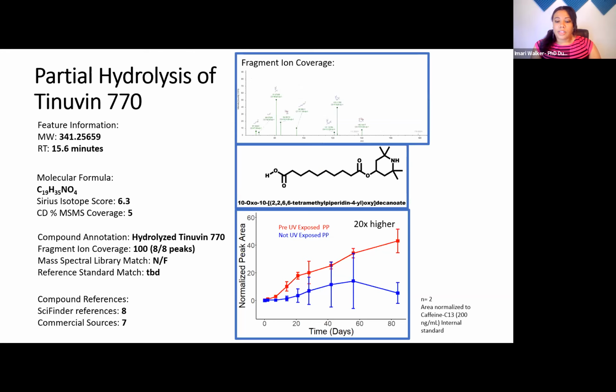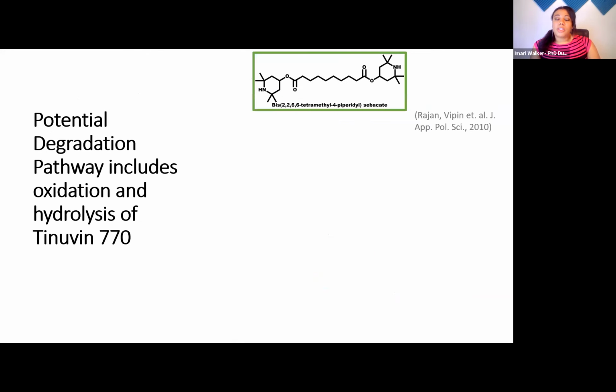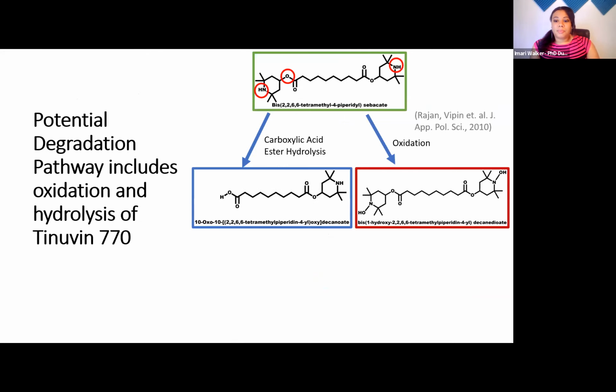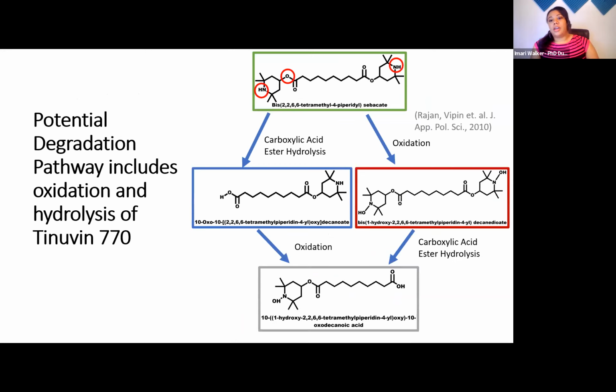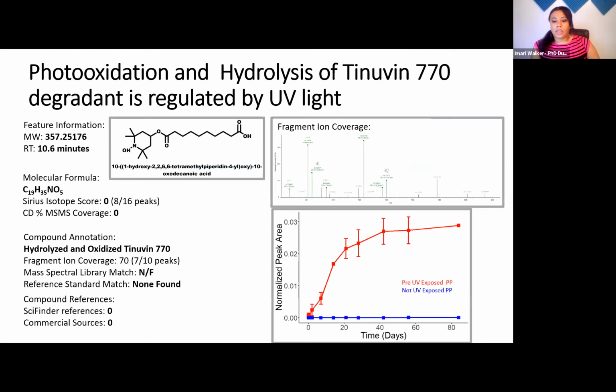Another compound, and this is just the confidence that we have using in silico fragmentation tools. Another potential degradation of Tinuvin 770 is actually hydrolysis followed by oxidation of the compound itself. And while this compound has never been seen in literature, it's what we propose with the structure and the matching of its mass spectral ion coverage. And it shows that with UV light, this is the only reason why it's present in these samples.